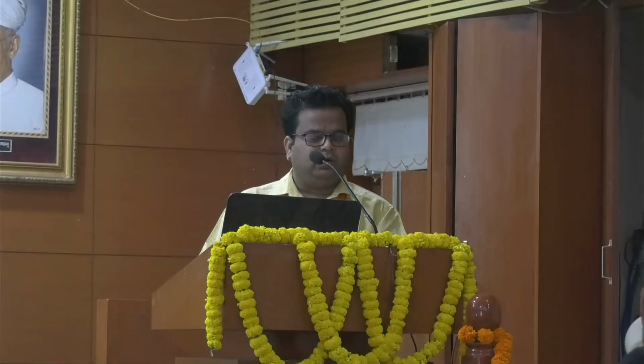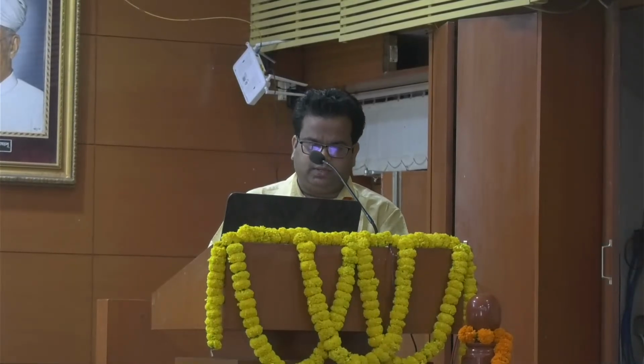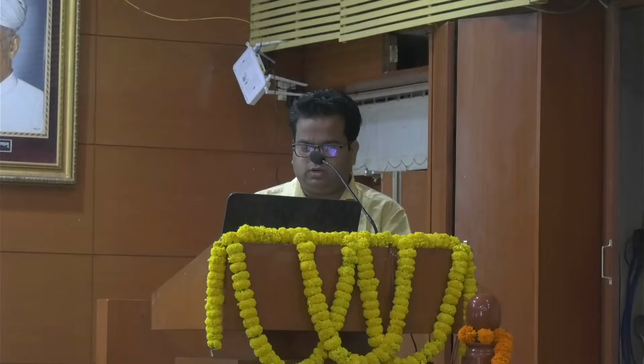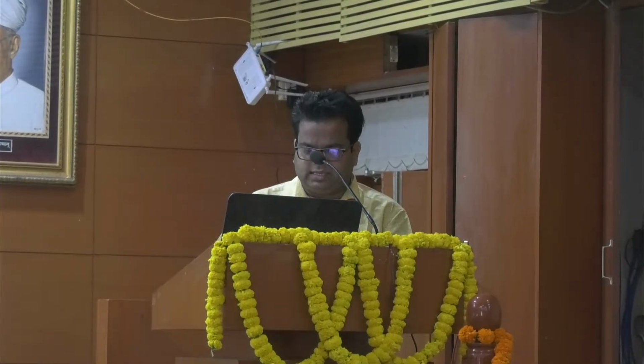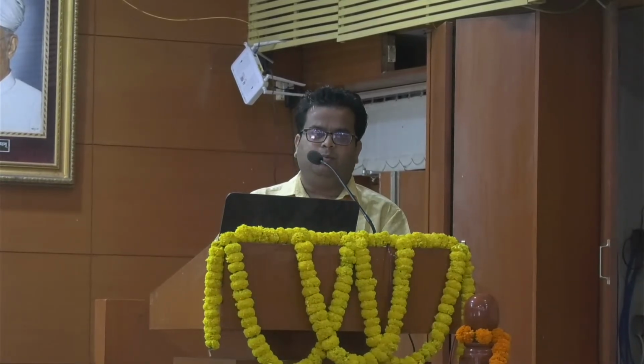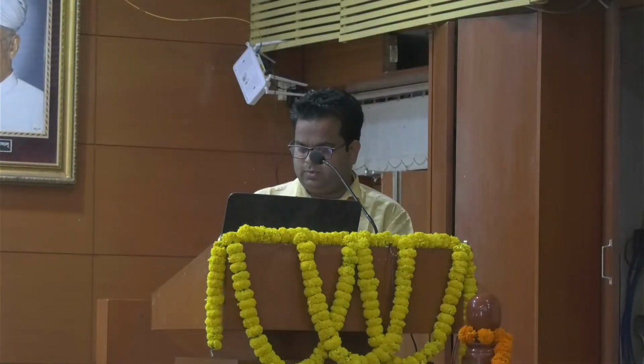First, we have collected waste eggshell from the local market, and we have cleaned it with clean water and air dried for 1 day. And after that, we put it in a hot air oven at 110 degrees Celsius for half an hour. After that, we ground it with the help of a mixer and mixed it with some herbal juice and produced calcium oxide nanoparticle by heating it at more than 1000 degrees Celsius for more than 3 hours.